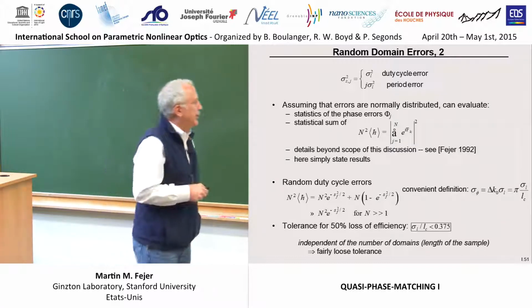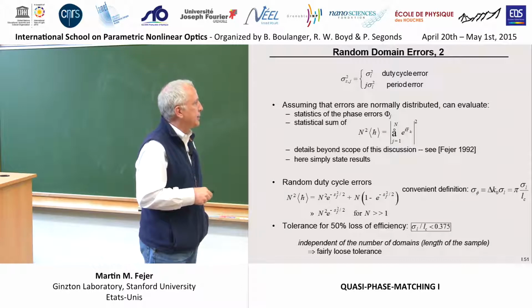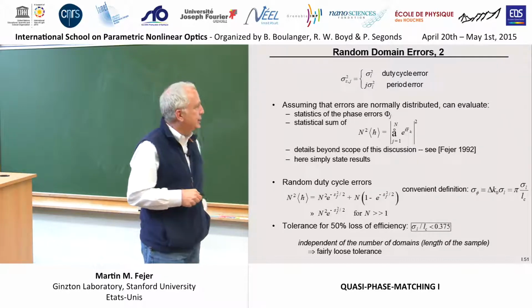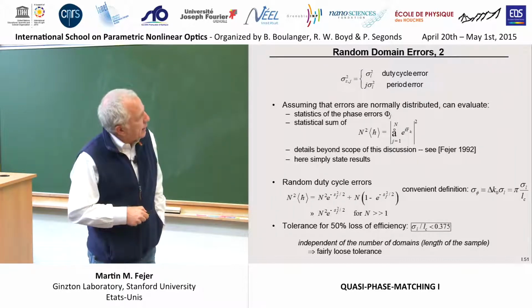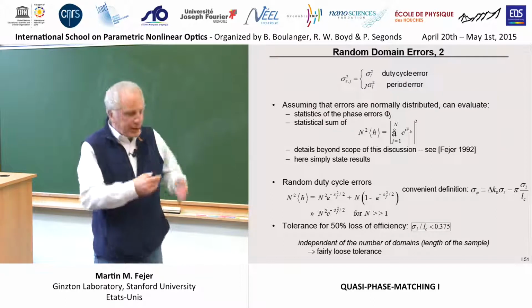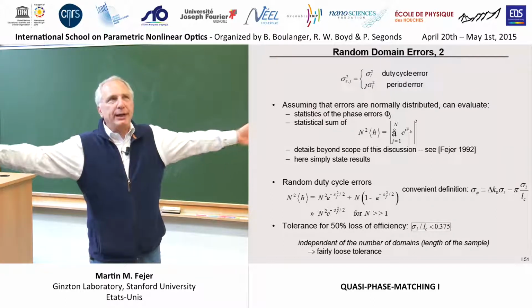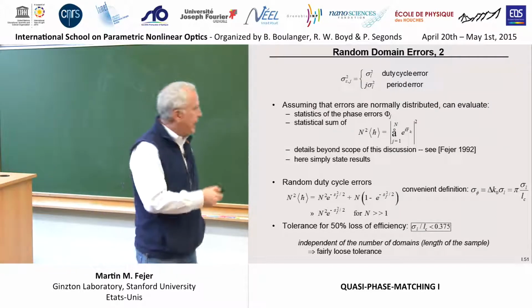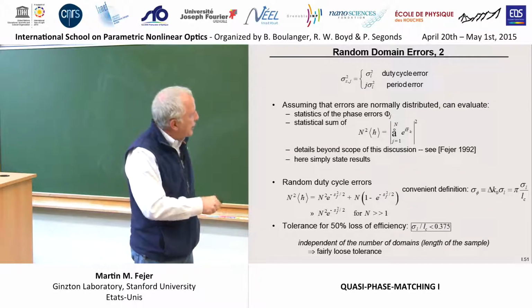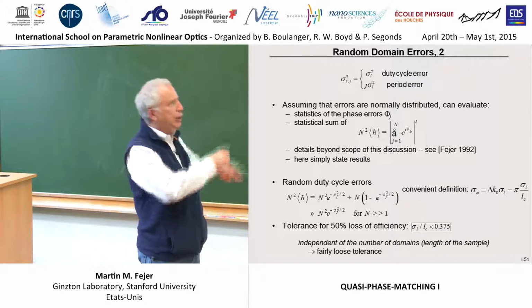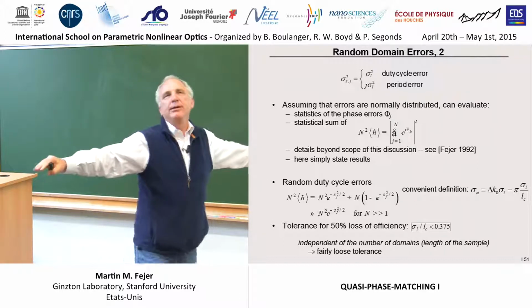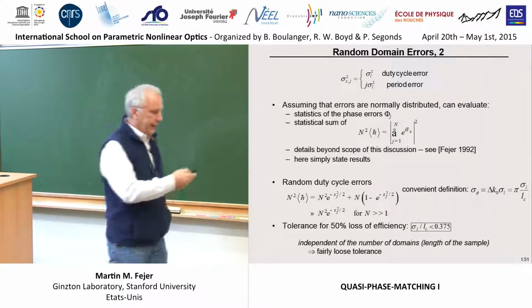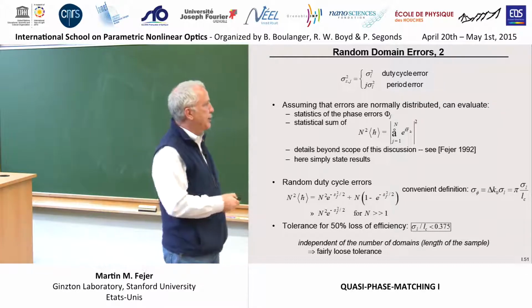And this thing is supposed to be eta. That's supposed to be the efficiency. So what do we see? We expect the efficiency to grow with n squared if the thing is perfect. If there are duty cycle errors, depending on how large this variance is, you reduce the peak efficiency. The tolerance isn't too tight for that.